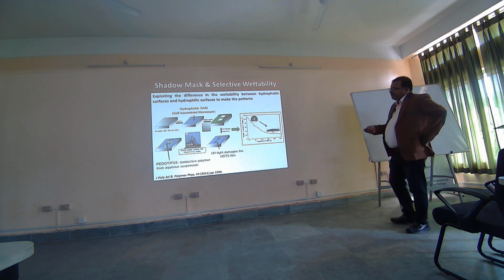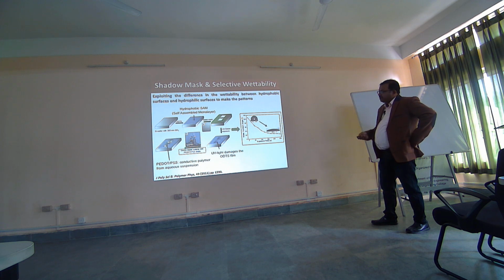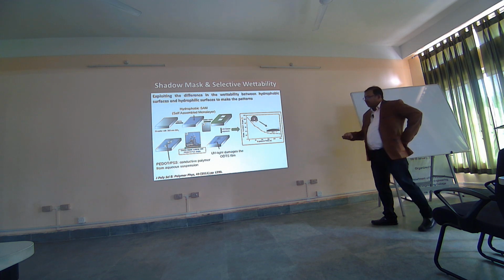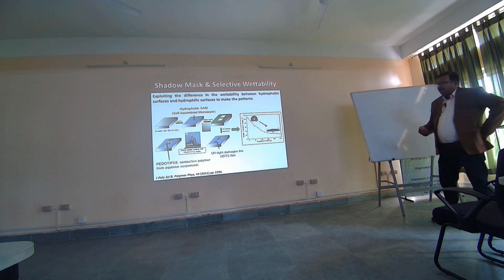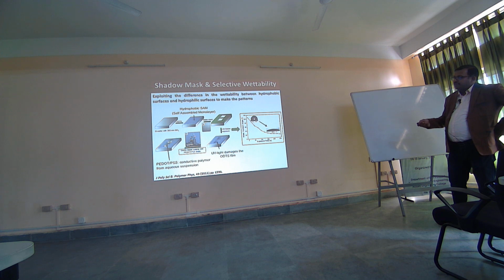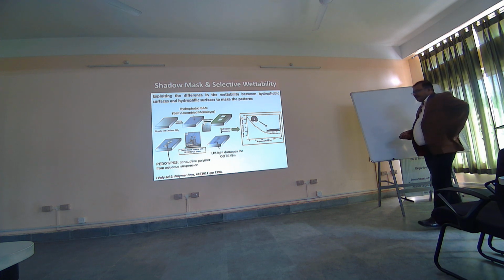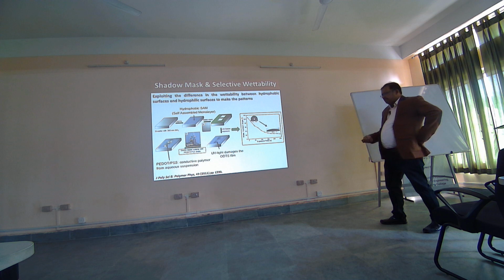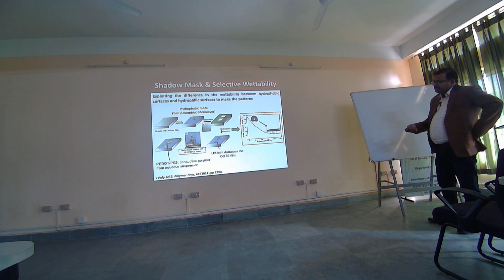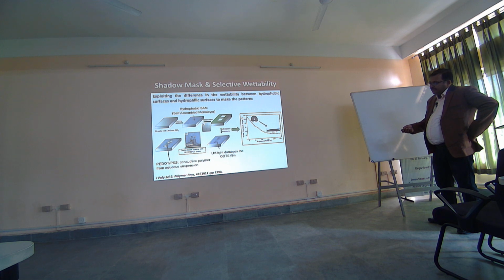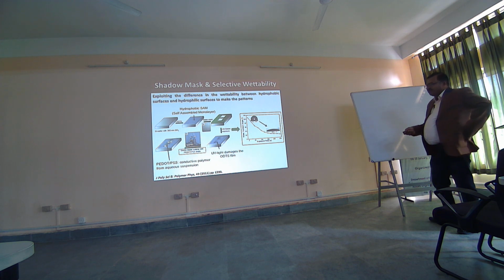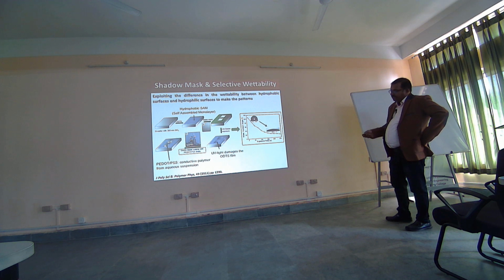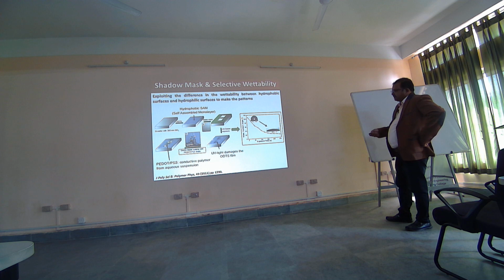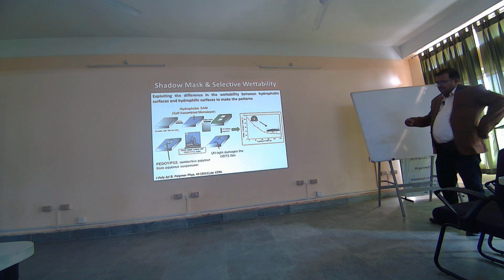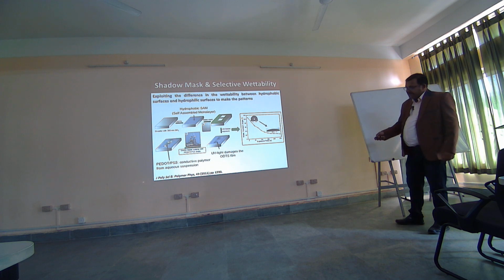And then we deposit metal. While depositing metal, because these metal electrodes are going to be the source drain electrodes for my organic field effect transistor, I use this kind of shadow masking technique to pattern these electrodes. Then if I illuminate with UV light, these source drain electrodes prevent the damage of the ODTS by the UV light below it, but otherwise it is damaged everywhere. There is of course some reason for the purpose of it, so you can refer to this paper.